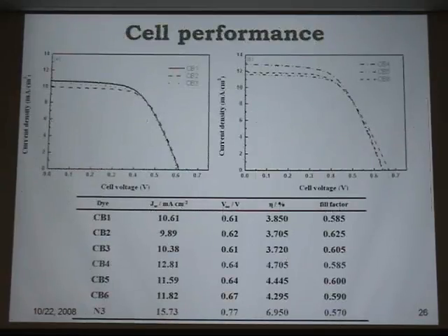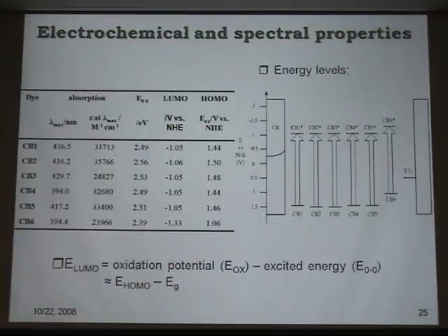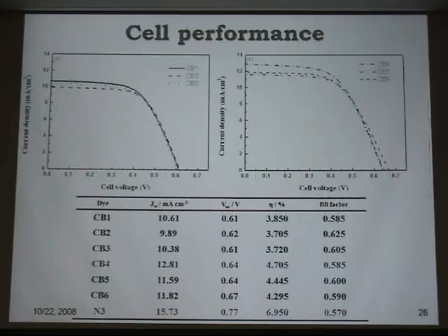So you take a look at the final performance compared to the N3 dye, for which we achieved around 6.95%. Number 6 actually did not perform the best. The best comes with number 4. So you cannot simply tell by the HOMO-LUMO pair. Something else has to be important.